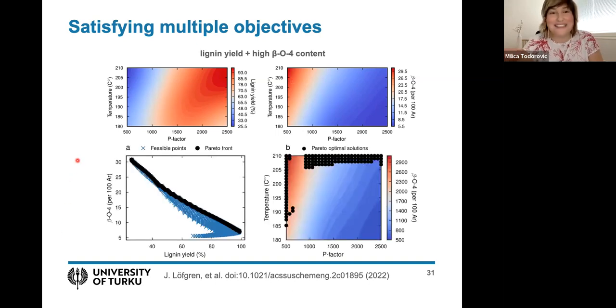So the way to do this, to satisfy multiple objectives, is to compute the Pareto front. These are all the Pareto points in the phase space of lignin yield versus beta O4. So between these two variables. And the black points here, which are the front of the blue points, is what is called the Pareto front. And they represent the optimal trade-offs between these two properties. And what the trade-offs tell us is that if we want to maximize one thing, we have to minimize another.